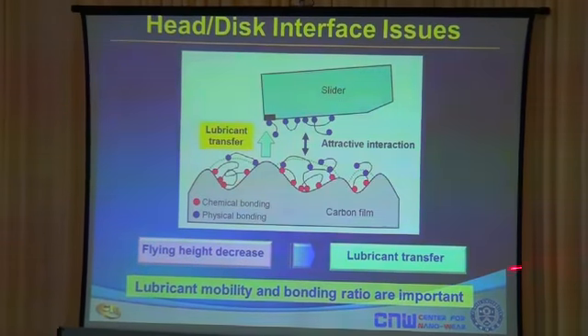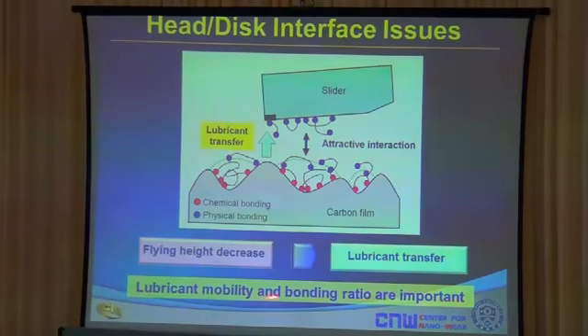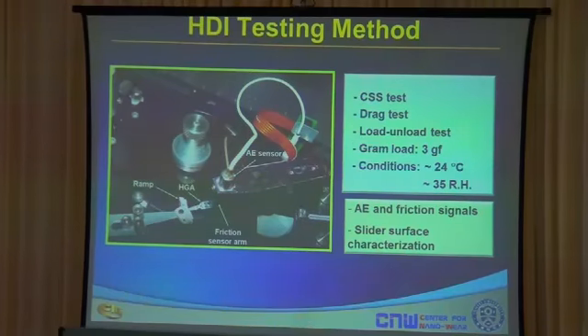And as the flying height decreases, the lubricant transfer occurs to a greater level, and as I told you before, lubricant mobility and bonding ratio is important. So first in this experiment, we want to see the effect of annealing, to see how annealing affects the flyability of the slider above the disc. And this is a simple test equipment. It's commercialized equipment that has a slider and a disc. This is a slider that you see here, and you cannot see the head, but the head is a very small thing at the end of the slider.